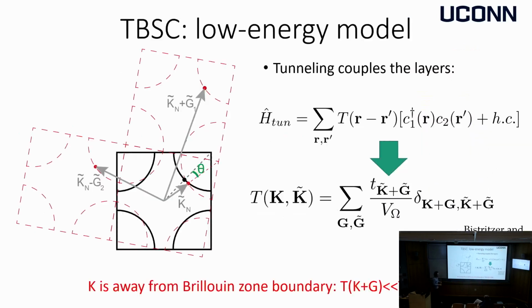And okay, just a few details for the, I guess, experts in the audience. So the way you do this, theoretically, is you want to construct some low-energy model, which really takes into account just these two Dirac cones, but you also need to be careful about how to take twist into account. So the way this works, you take the Brillouin zone of a single layer, and you take the other layer, and you take all possible Brillouin zones, and you rotate them with the twist angle.